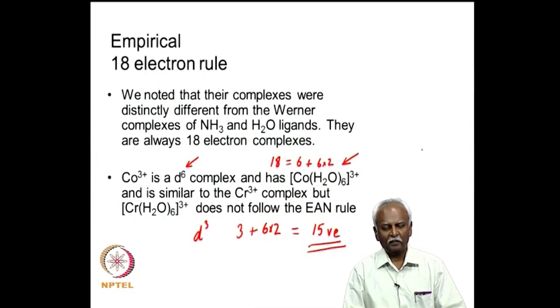What we have noted is that the organometallic complexes that we are encountering in these systems strictly follow an 18 electron rule. And this is very different from Werner's coordination chemistry, where you only have an octahedral complex being formed or a tetrahedral complex, and the driving force seems to be the restriction on the coordination number and geometry rather than on the valence electron count.